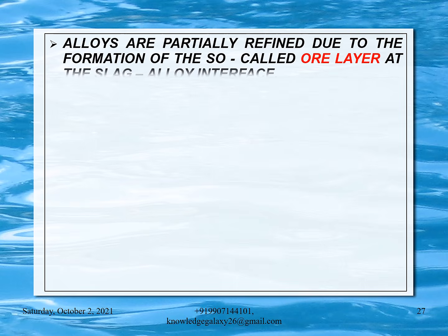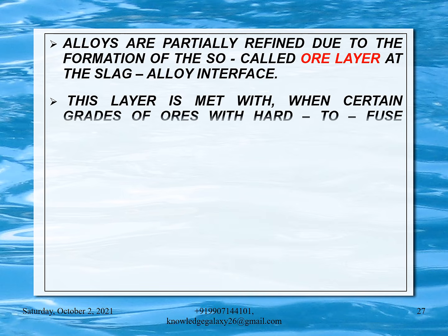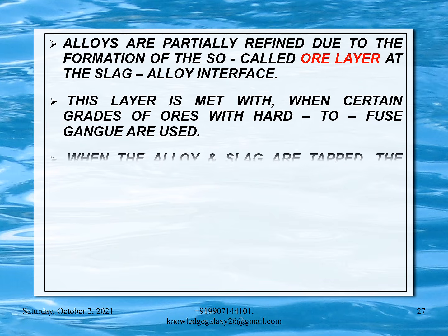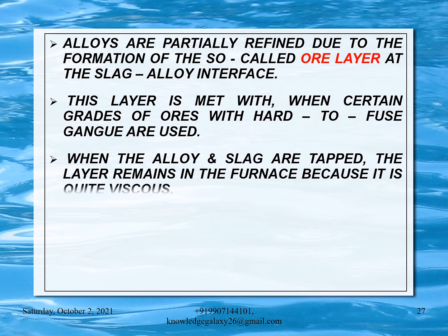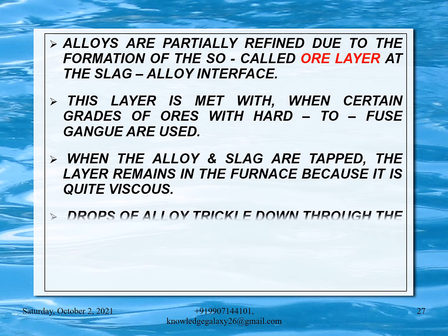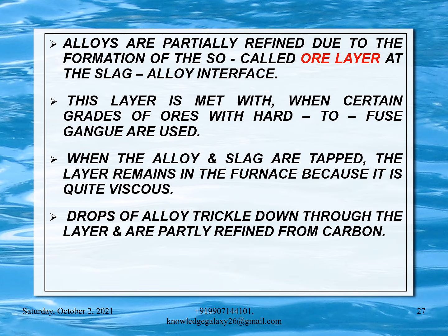Alloys are partially refined due to the formation of the so-called ore layer at the slag-alloy interface. This layer is met with when certain grades of ores with hard-to-fuse gangue are used. When the alloy and slag are tapped, the layer remains in the furnace because it is quite viscous. Drops of alloy trickle down through the layer and are partly refined from carbon.